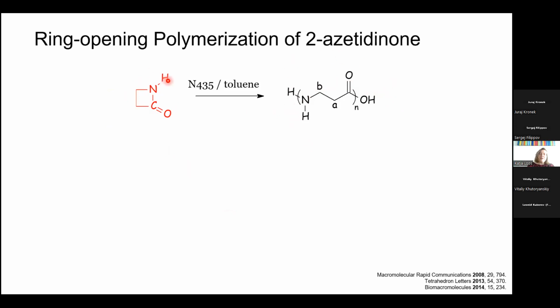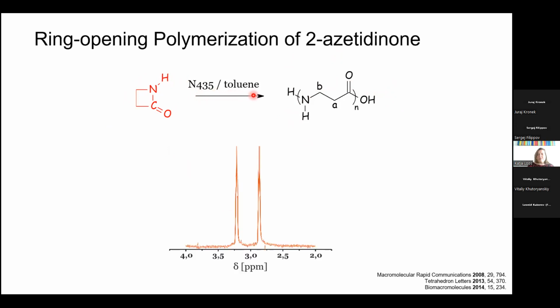And yeah, we just tried immobilized Cal-B in toluene, and you really see it works. It's the NMR spectrum of the educt and of the product, and it goes to very high conversion. But the big problem with polyamides, of course, is their bad solubility in anything, and the things that solubilize polyamides, or at least a bit, for instance NMP with lithium chloride, no enzyme would survive that, because in principle the enzyme is of course also a polyamide. It's a polyamide of amino acids.